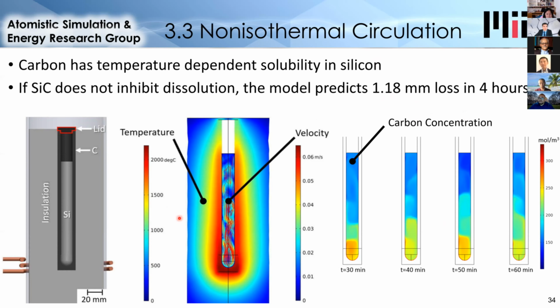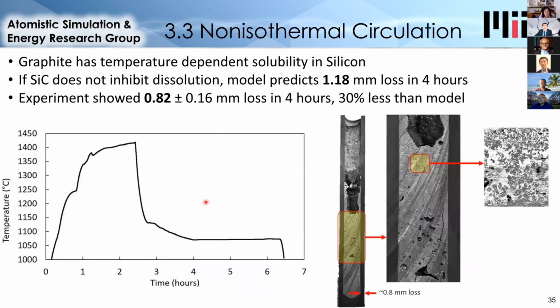So I ran an experiment based on the temperature conditions in this model and found that, in fact, carbon does dissolve at almost this rate. So we predicted 1.18 millimeters, and I measured 0.82 millimeters loss. The reason the loss is slightly smaller is most likely because the carbon that dissolved, when it redeposited in the top of the tank as a solid, started to block the flow path and reduce the convection currents. But what this shows is that, in fact, carbon does dissolve despite the presence of a silicon carbide layer. And this is a major issue for this technology because there's no way to really avoid the non-isothermal circulation when we need to move silicon from the hot tank to the cold tank in order to use the energy stored.